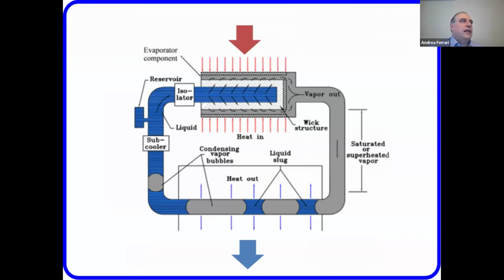So the idea is to use capillary pressure - to use a metal wick with some pores. When this is heated up by internal or external heat sources, it evaporates a fluid circulating within the satellite, removing the heat, and then there is condensation, evaporation, condensation, evaporation.